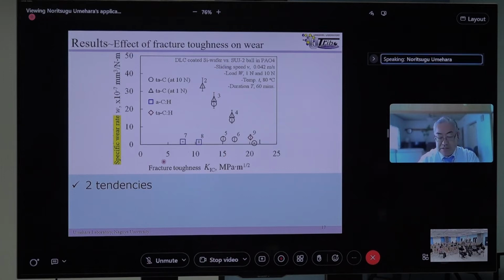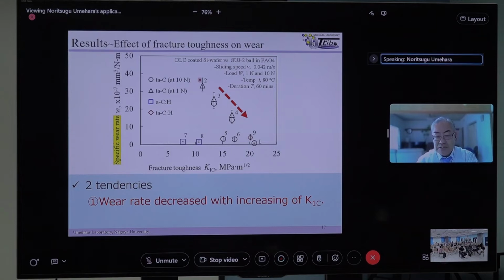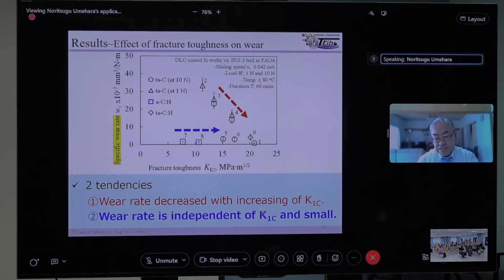One tendency is that the wear rate decreases with increasing K1C. The other is that the wear rate is independent of K1C and quite small. Still there are two tendencies. We have to get a total concept to control the wear of DLC. What explains these tendencies?